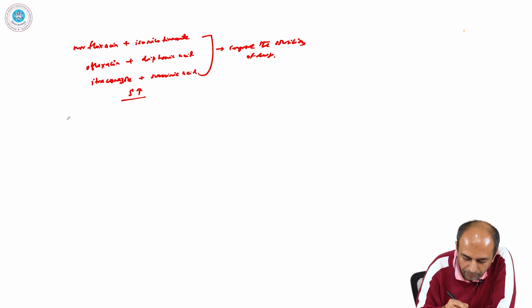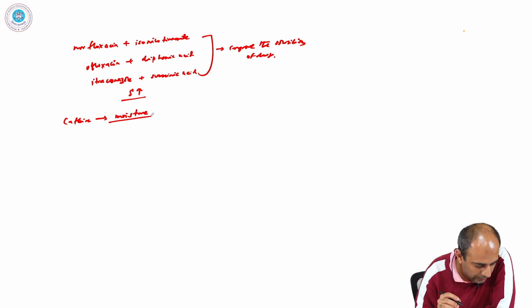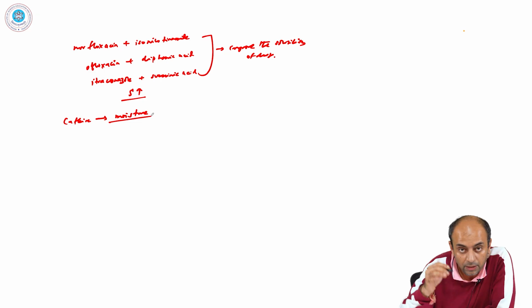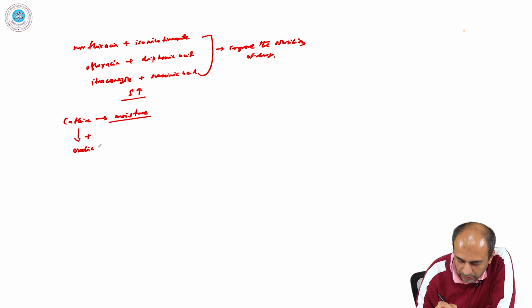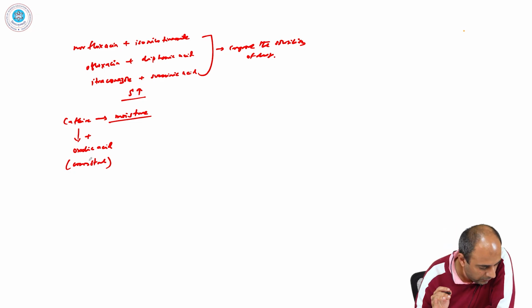So, in this regard, caffeine is very sensitive to moisture, and there are problems associated with storage, because it is susceptible to hydration with change in the atmospheric or humidity conditions outside. And this caffeine is now stabilized by forming a co-crystal with oxalic acid.